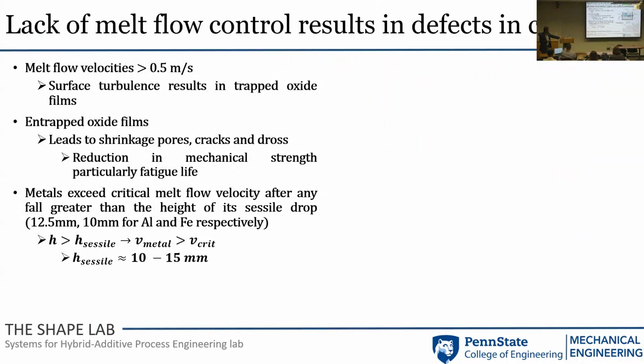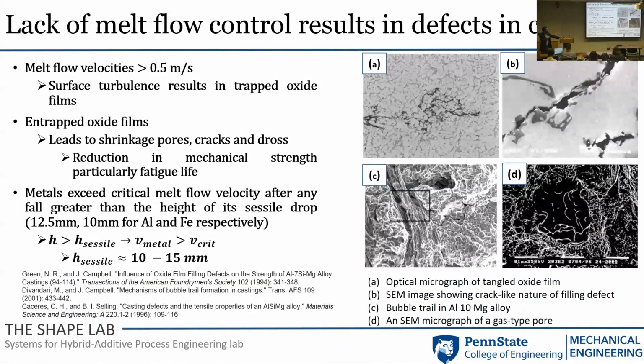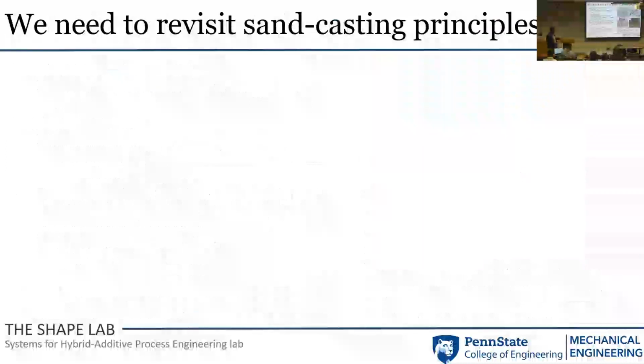Oxides, as you know, and fatigue is not good. And that's why if you go back to your mechanical design courses, the factor of safety for casting, the first rule of thumb is do not use castings for fatigue applications. And if you're going to use it for anything, you have a safety factor of 3 to 5 minimum. The reason being lack of melt flow control, and the literature across different alloys, whether it is aluminum, steel, iron, and so forth, and across different part geometries is full of parts that show you have oxide films, you have cracks, you have bubble trails, and so forth.